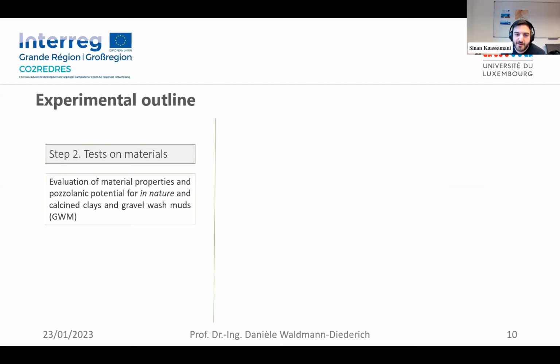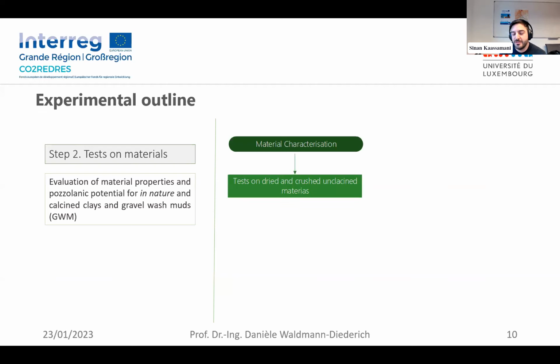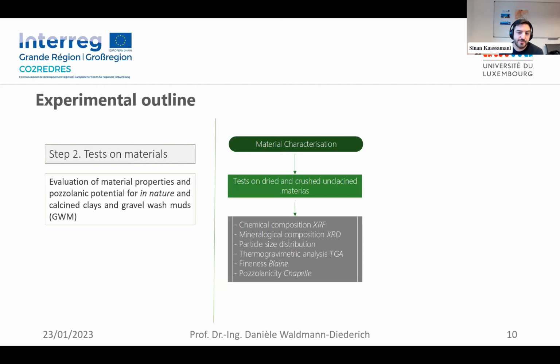So for the second step of our project, we evaluated the properties of these materials. So the in natura, right, the pure material, and also the calcined material. On the material characterization front, we ran tests on dried and crushed uncalcined materials, such as chemical composition, mineralogy, fineness, particle size distribution, TGA, and pozzolanicity as well. I will not show all these results because it will take too much time. But it's interesting to comment on what we actually looked for.